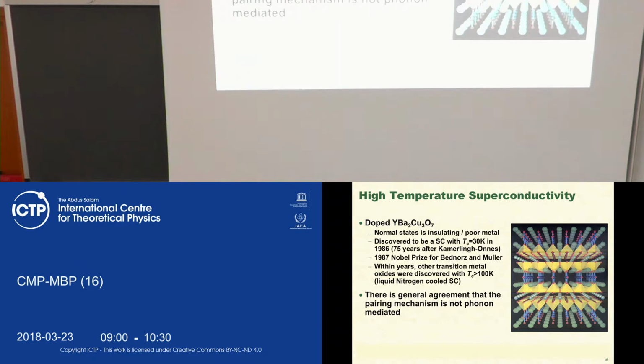So the message which is written here says that it's now experimental evidence that the pairing mechanism is not the phonon mechanism. In addition to the fact that this system is a real high temperature superconductor, it also tells us that the mechanism of such superconductivity is different from the mechanism explaining superconductivity in a simple compound. Therefore, as I said, the challenge is first of all to understand this mechanism.